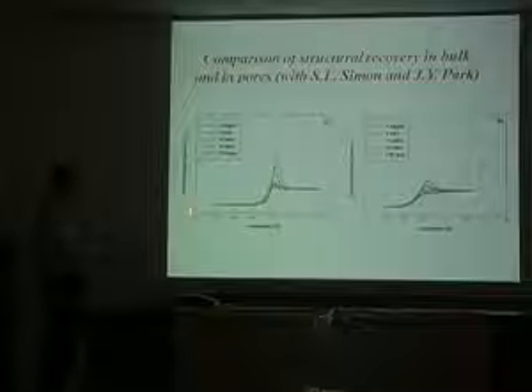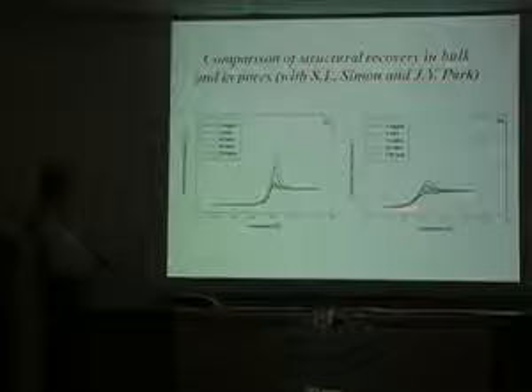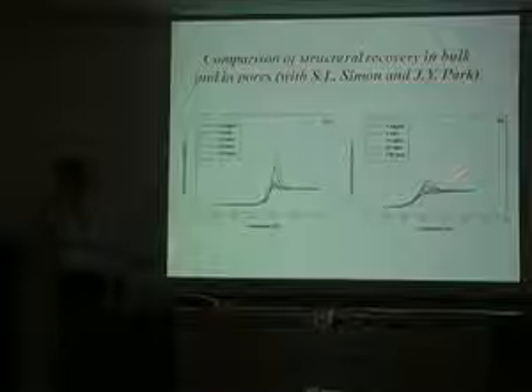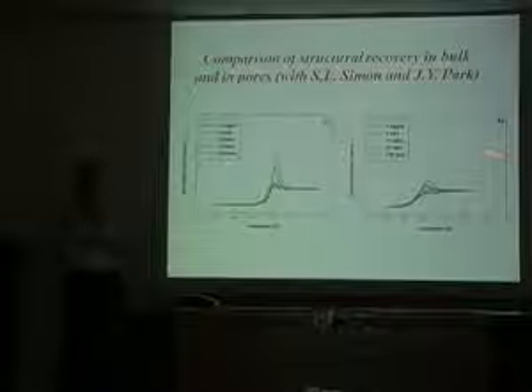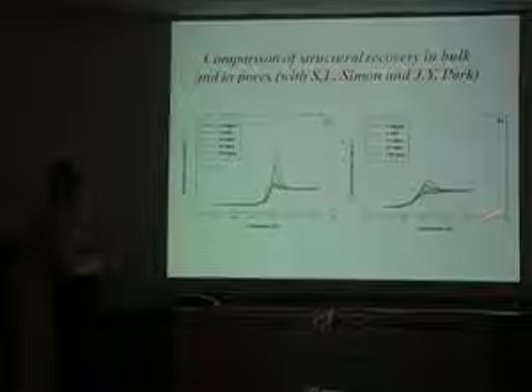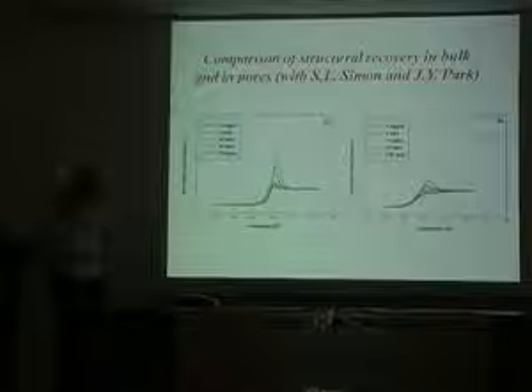Here's the typical behavior, okay? This is the bulk normalized heat capacity, so you can see as you age it, this big buildup in the excess enthalpy. Whereas when we put it into a pore, and this is the 11 nanometer pore, I'm sorry I don't have it on there, we see that it looks like the enthalpy is building up much less. Okay? So the question is the aging rate slowing down, or is there something else going on? I mean, we had done some work back in the 90s thinking that this was slowed down aging in the nanopores. But we now don't think that's the case, and here's the reason why.